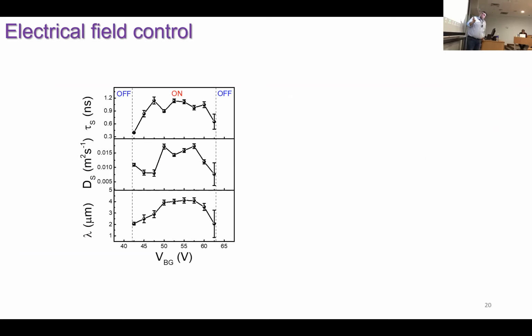So basically, we did some spin transport measurements with this sample, as a function of gate voltage. Here you can see that there is no spin transport until this gate voltage range, which can be understood as the material being within the band gap. So your Fermi level was within the band gap, so there is nothing to carry. And then we were seeing nice spin transport, and later on again, the spin transport disappears. This part is quite strange, especially once your device is conducting even better, but you don't see any spin transport. So you have this off, on, and off structure as a function of gate voltage.